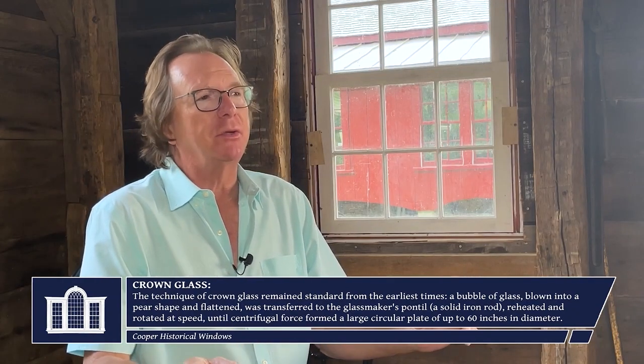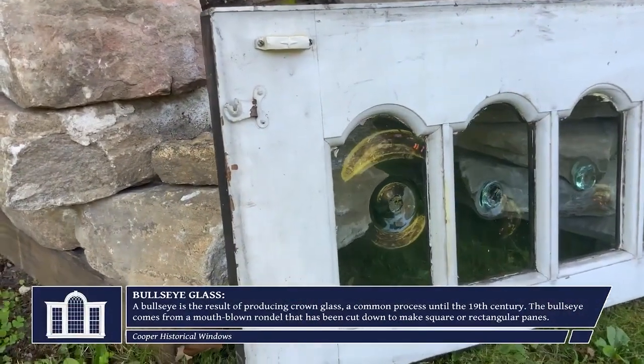The 18th century glass was referred to as crown glass and was the most prized of all because it was hand blown and had the circular lines in it as a result of the spinning process that was used to expand the glass mandrel. It was spun until the glass was the right thickness, and this was done using a pontil or blowpipe to first blow the molten glass bubble. Then a second pontil or punty was attached to finish the process. This mark or scar left from the pontil was the earmark for what is known as today's bullseye glass.